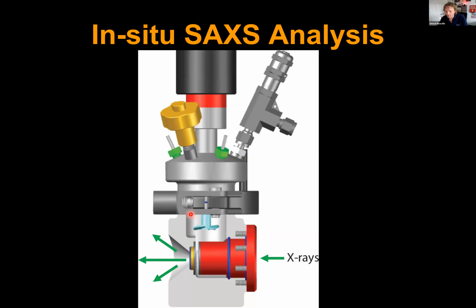One of the questions that we asked is, can we watch this process? Could we actually follow the reaction as it happened? For this, we decided that we needed to turn to doing some scattering measurements, and we used some small angle X-ray scattering. But a small angle X-ray scattering cell for working at such high pressures wasn't readily available, it didn't really exist, so we actually had to make one ourselves. And you can see it's based on the autoclave that I showed you earlier.